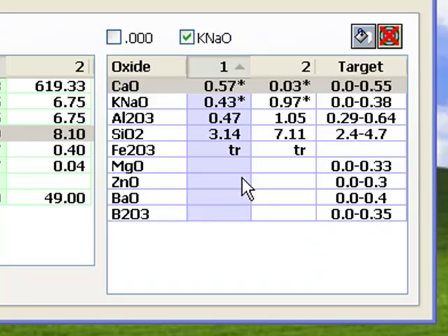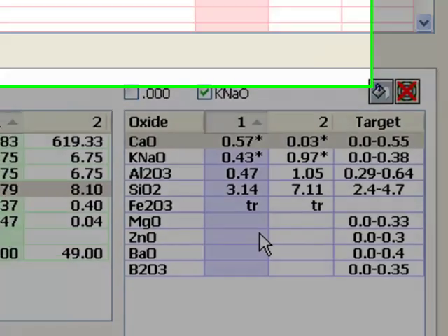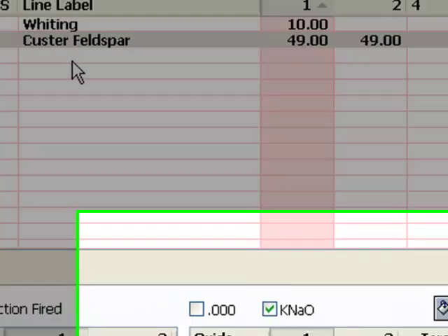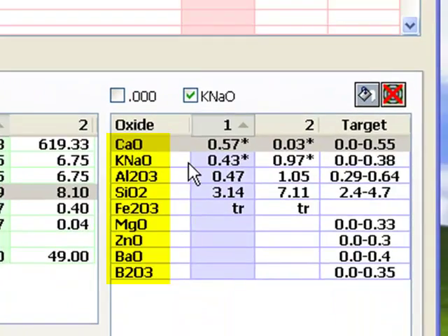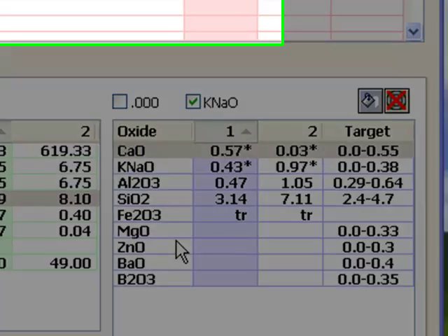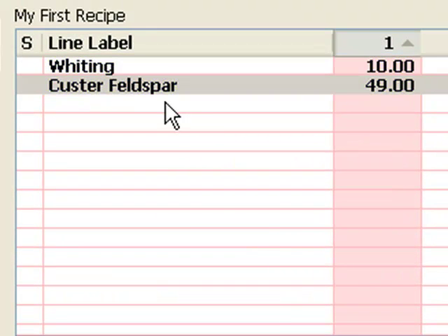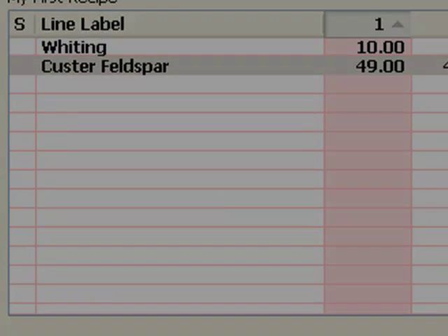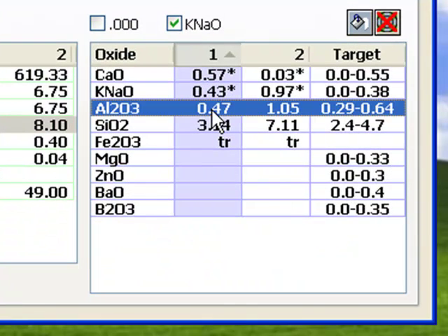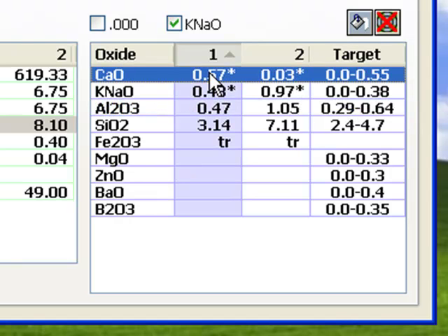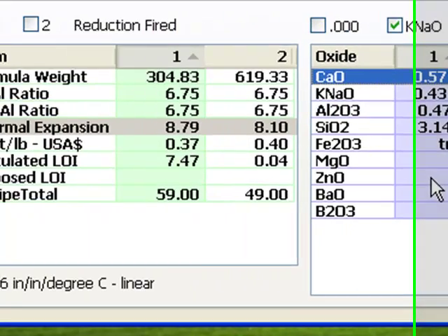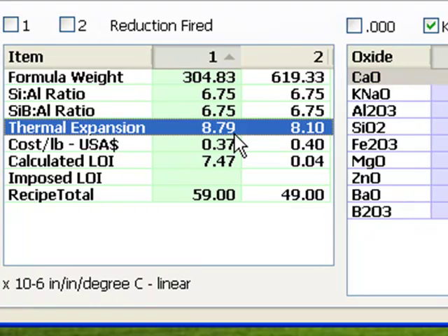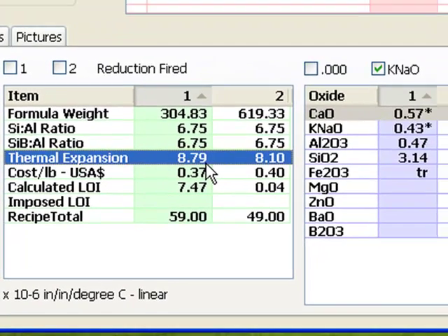As you will see, in glaze chemistry we see materials as sources of oxides. Could this two-material glaze work on stoneware at cone 10? Yes, at least it would melt very well. How about cone 6? No. A glaze with this high alumina needs a melter more powerful than CaO, for example, boron from a frit. In addition, the thermal expansion is still much too high and crazing is virtually certain. The KNaO is way too high.